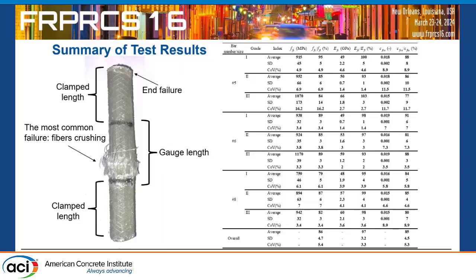This is the kind of failure that we saw the majority of the time, in terms of the crushing of the bars, microbuckling of the fibers. This microbuckling has been in the literature, and everybody refers to that one, but it's not happening that early. And so here are all results. Compression over tension in terms of percentage, we have an average of 86% in total. In terms of coefficient of variation, very little, 5%. There are some cases where we had 16%, but overall on average we have around 5% variation, which is very good.